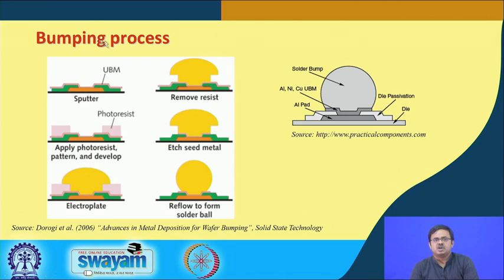Okay. So, this is the process of bumping, and if you look at the right hand side picture, you see another schematic, and again, this is the die, this is the aluminum pad. We could not have deposited this solder bump on this dark gray aluminum, so I had to do an under bump metallization. Once I did the under bump metallization, I go through this process described on the left, and finally end up with the solder ball or the solder bump deposited over this site, the connection pad that had the UBM layer. Agree? So, this is the bumping process.